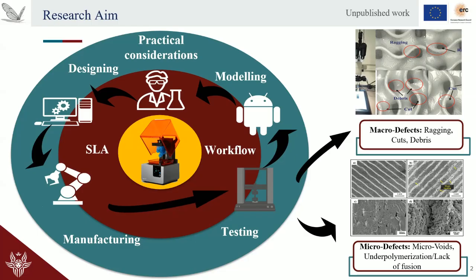For example, what can happen are some macro defects or, more importantly, some micro defects, such as microvoids, underpolymerization, or lack of fusion in SLM printing. And that influences hugely both static and dynamic behavior of the components. So to break free from this cycle, we have to improve the modeling solution. It doesn't have to be a weak model, but a strong model, so that it can break the loop at the first iteration.